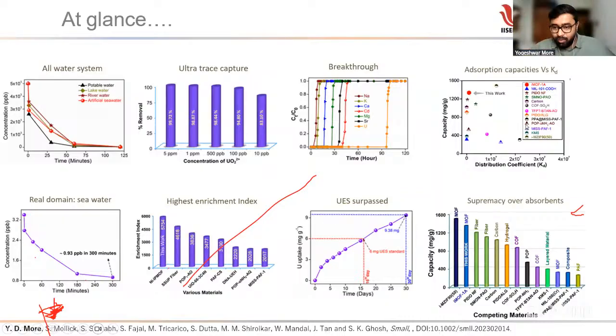Then now we have to map globally all the commercial adsorbents present for uranium extraction. So our MOF ranks here, in the capacity versus distribution coefficient graph. So what is capacity versus distribution coefficient? You should have a higher capacity, meaning the amount of uranium the adsorbent can hold. But you should have a higher distribution coefficient as well, meaning the distribution should be very fast. So an adsorbent can even have lower capacity, but if the distribution is fast, you can reuse it and extract more uranium. In this case, our MOF has the second highest capacity in the reported domain, but a significantly lower distribution coefficient. That means this MOF can be deployed for a longer time in the seawater to extract the uranium. That is its outcome.